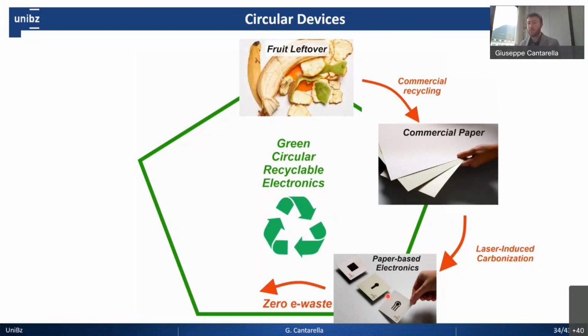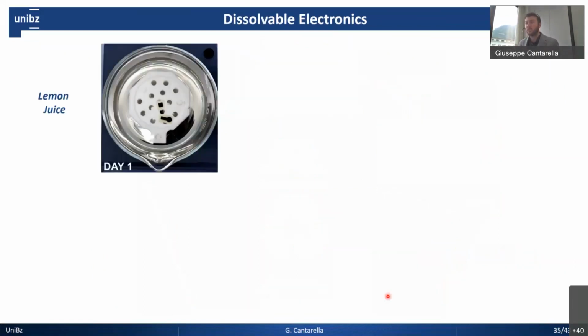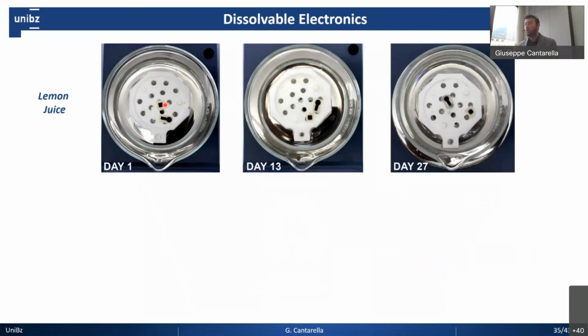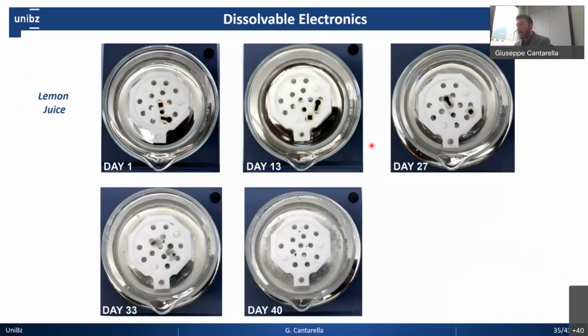So following still the circle, we ended up at this point in which our electronics could be functional using this approach. We thought, would it be possible to make these electronics dissolvable? So after usage, just dissolve it. So this is what we did. We take a lemon juice solution, so mostly citric acid, and two small paper-based electrodes, and we monitor what was going on at different days. As you can see here, at day 27, what we experience is that the cellulose is highly damaged and is almost gone. And then at day 33, and then finally at day 40, even the carbonized part is completely gone. So as you can see here, in 4 weeks the cellulose is almost gone, and after almost 6 weeks there are no residuals of our devices.